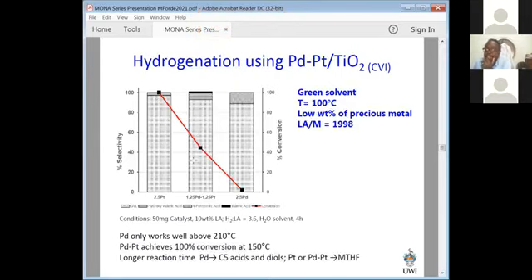Now, usually you have to have very high pressure of hydrogen, because levulinic acid is not so easy to work with, and obviously high temperature. And depending on your catalyst system, the levulinic acid can actually dissolve your catalyst. So that's also a consideration. We did this work with the same materials and found that platinum was really good. Palladium wasn't as good, but also had high selectivity. Palladium didn't work very well unless you cranked up the temperature a lot here. And this is a solventless system, or a solvent system of water, where you dissolve levulinic acid in water at high weight % of the substrate and use a very small amount of catalyst, right? So the turnover number is actually quite high.